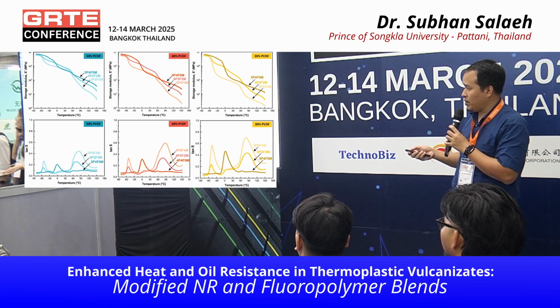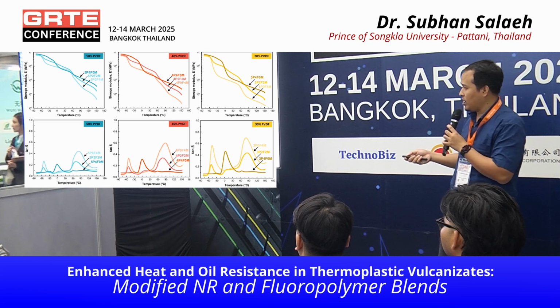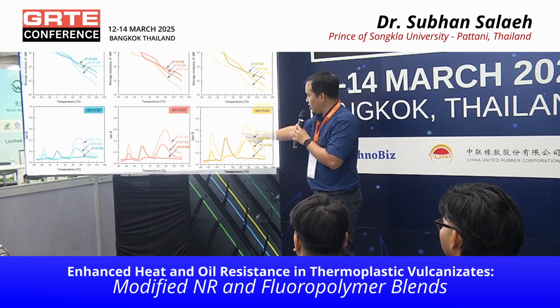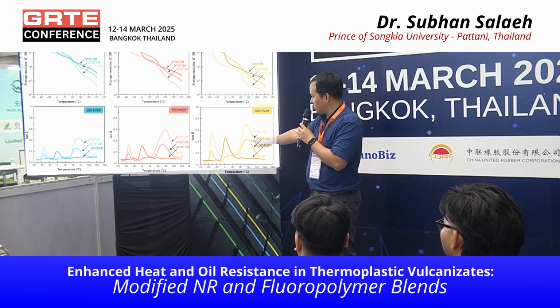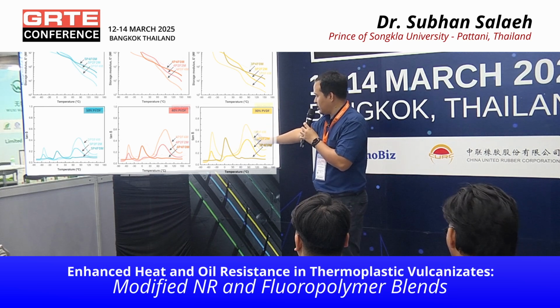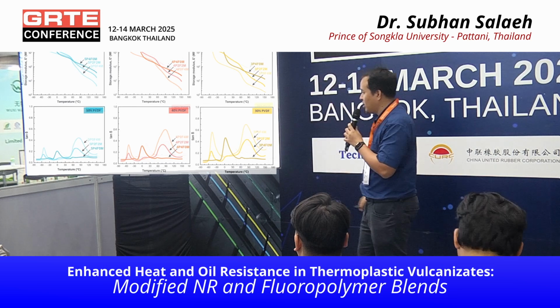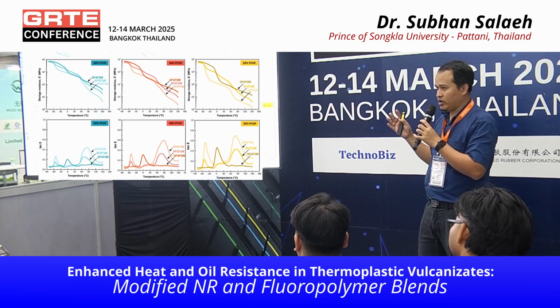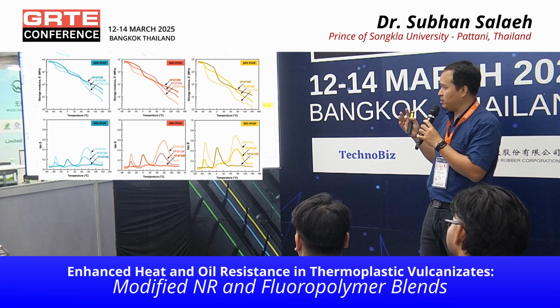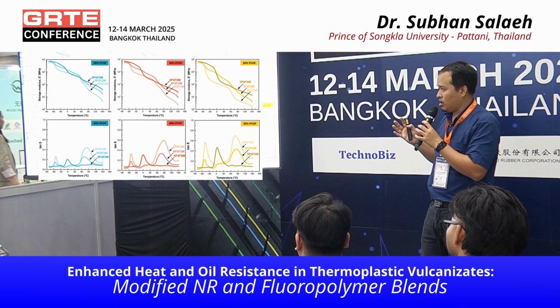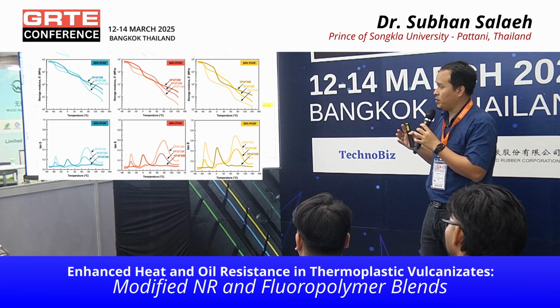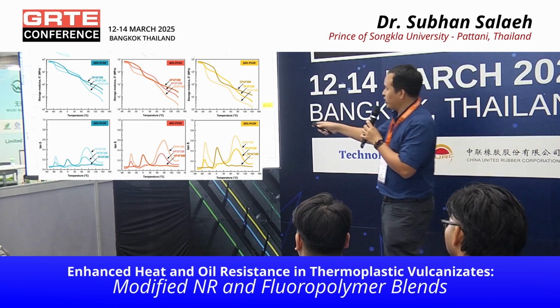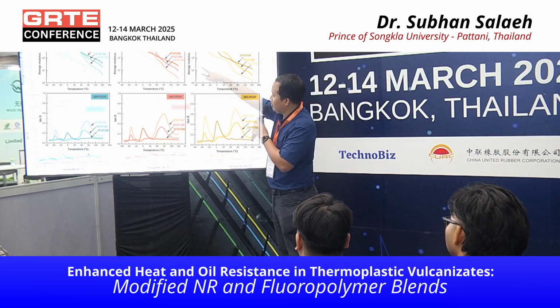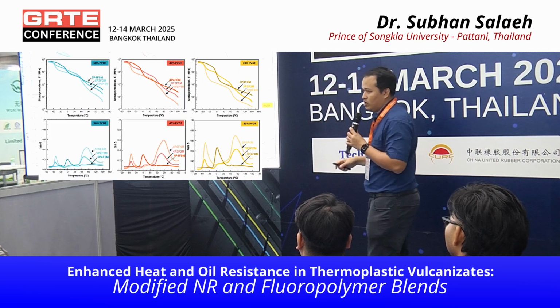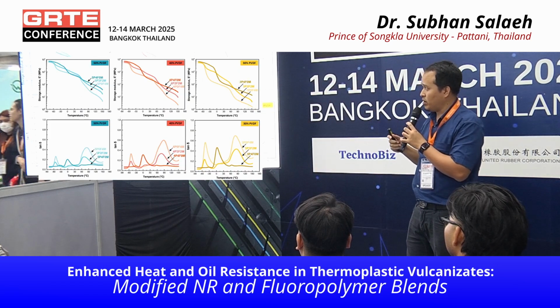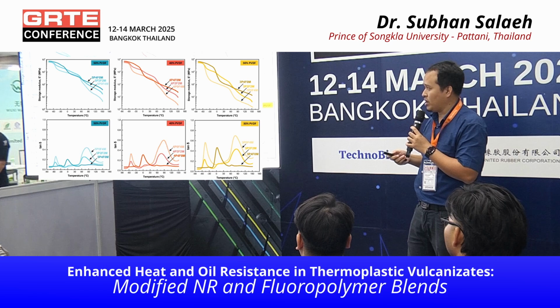And this is the DMA curve. So we can see the Tg of each component in the TPV. Usually we can see the shifting of the Tg of each phase, which is due to the miscibility between the blend components in this TPV. And then we can see that the ternary blend shows higher modulus than the binary blend due to the good interaction between PVDF, FKM, and MGNR.